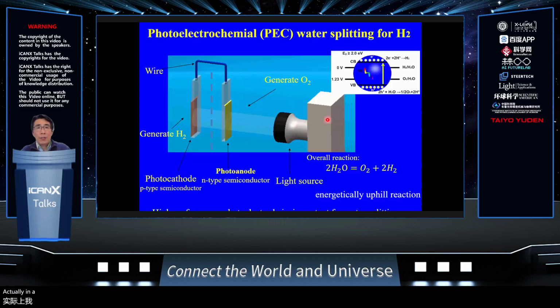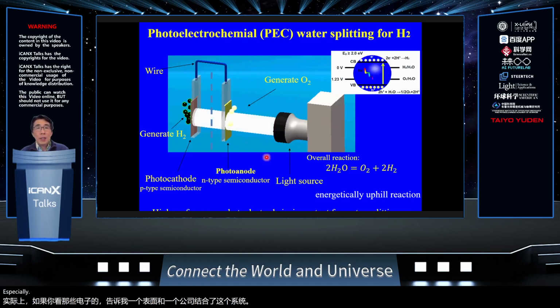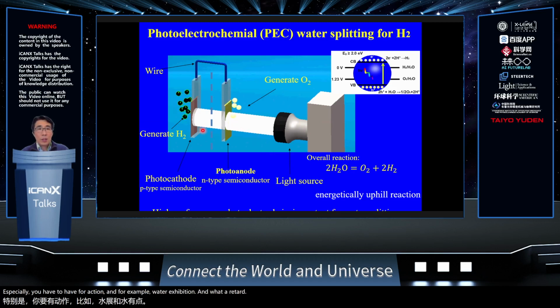Actually, if you look at the photoelectrochemical process, that's a combined system. You have two half reactions, for example, water oxidation and water reduction, and we want these two reactions to happen on two electrodes. In between, we have a wire to connect and to apply a small bias, which can help the charge transfer from one side to another. This also will reduce the recombination. In this case, the hydrogen and oxygen will be produced separately without any further separation process. That's what we have been working on in the past 7 or 8 years.